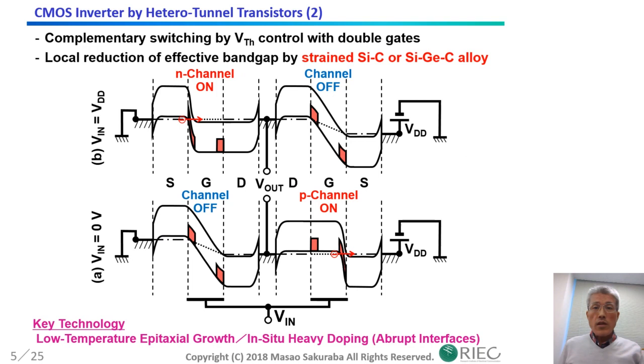Corresponding energy band structures are considered like these figures. Quantum tunneling is highly sensitive to tunneling distance, and the distance should be precisely controlled in nanometer order. Therefore, I believe that the key technology is energy band modulation using nanometer scale heterostructure and local doping. In this way, we should suppress intermixing at interfaces.